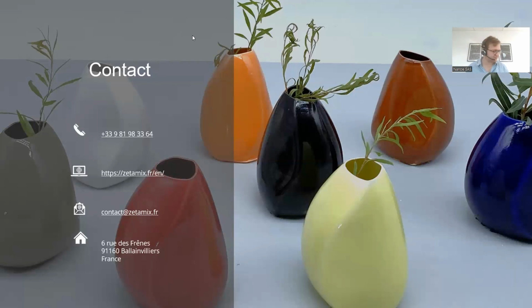Of course, if I was to print that vase in 0.4 millimeter, I'm not 100% sure that it would survive the sintering process. So this one was printed with, I think, a 1 millimeter layer thickness, but it depends on your design. The higher it's going to be, the more you're going to need relatively thick walls so that it survives the sintering process and to avoid any deformation.